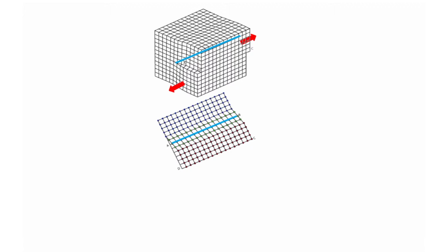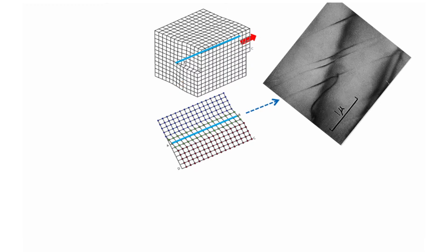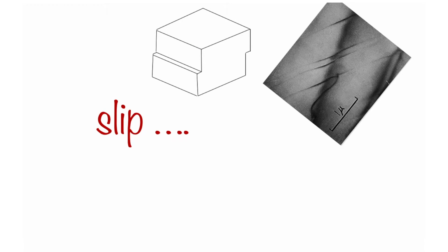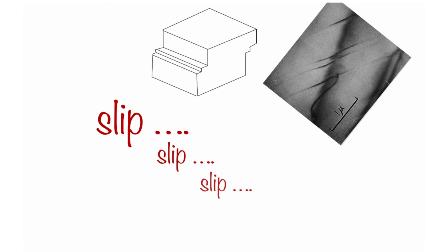And then we look at this structure from the top. That is what you would see in an electron microscope, in a transmission electron microscope. There's a blue line, and then I show the picture. There we are. This is the image of dislocations. Now, if we keep pulling this material, we're shearing it, then zip, the dislocation moves across and leaves behind a slip edge along the whole crystal, which displaces the top half with respect to the bottom half.